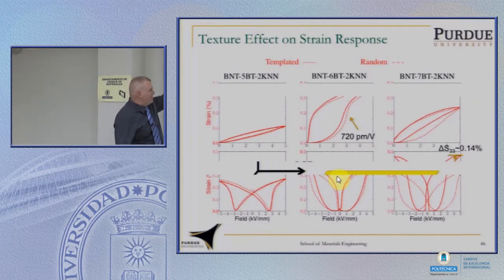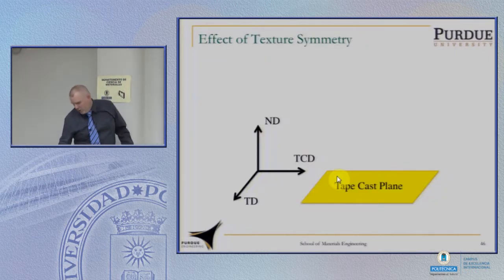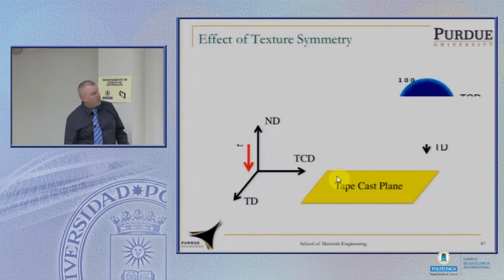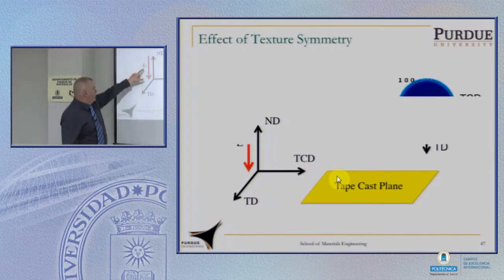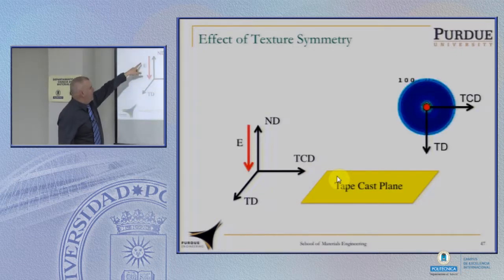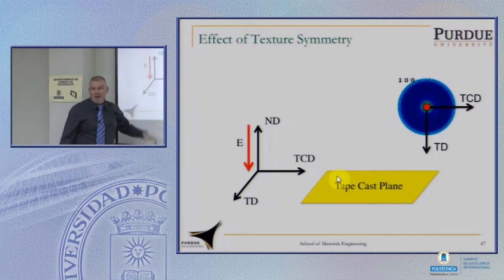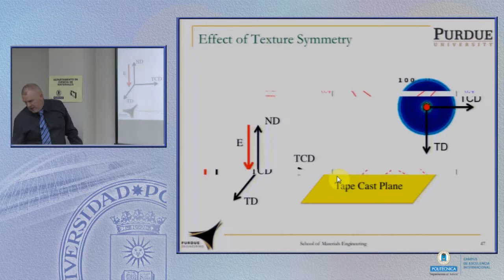So these materials were made. This is the coordinate system, the tape casting plane. And Chris wanted to study the effects of applying field. So we made samples where we could apply the electric field in this direction. So it's the direction along which there's a lot of orientation. And then went through and made the strain measurements.